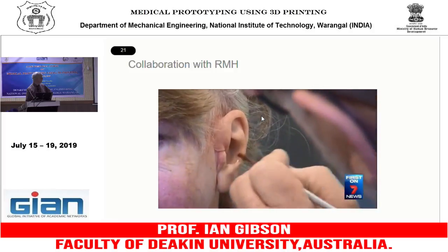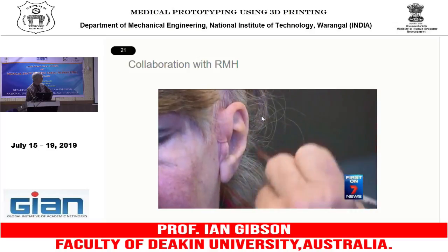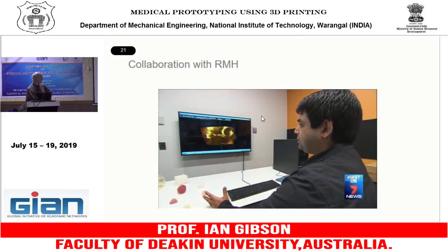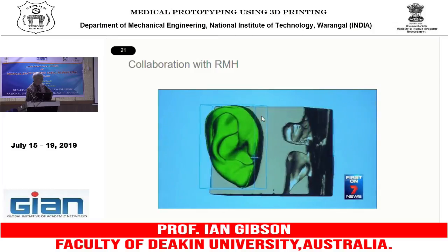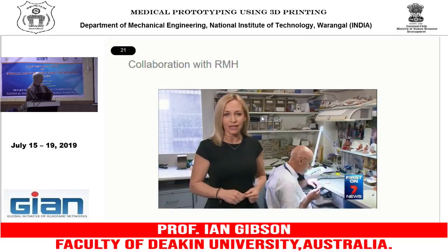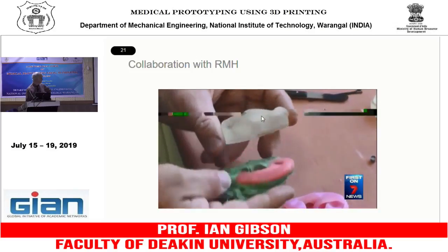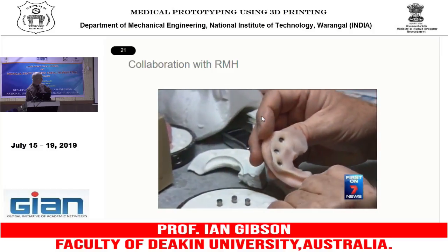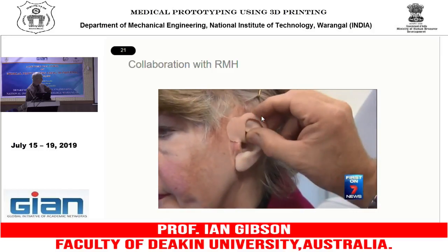Colleen's lifelike new ear is the first in Australia to be made using 3D printing technology. What we offer with our techniques is a like-for-like 100% reproduction of that patient's own anatomy, which you just can't ask for better than that. The process began with 3D medical imaging of Colleen's head. Then, by isolating her right ear, technicians at Geelong's Deakin University were able to use data to print a digital mirror image, which became the model for her new prosthetic. Using the 3D printed model prosthesis at the Royal Melbourne Hospital, they were then able to create Colleen the perfect ear. A mould was produced for the silicone ear before the final touches were made, preparing Colleen's new body part. Months were spent perfecting the new ear, which snaps magnetically onto titanium stumps surgically implanted into Colleen's head.